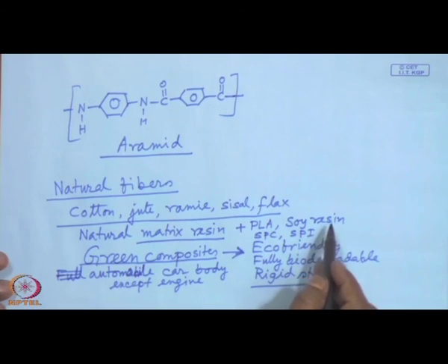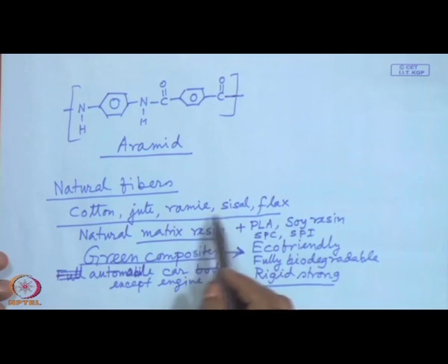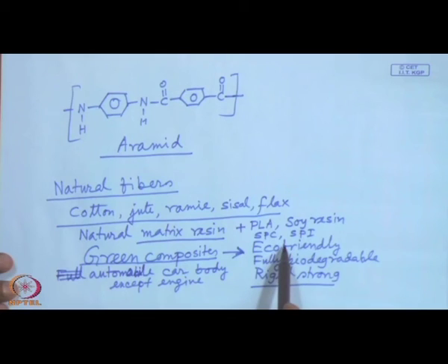Now, this soy resin, SPC and SPI, along with sisal or ramie or flax, have been found to yield very strong green composite, which is rigid, stiff, tough, but biodegradable. The resin is hydrophilic.